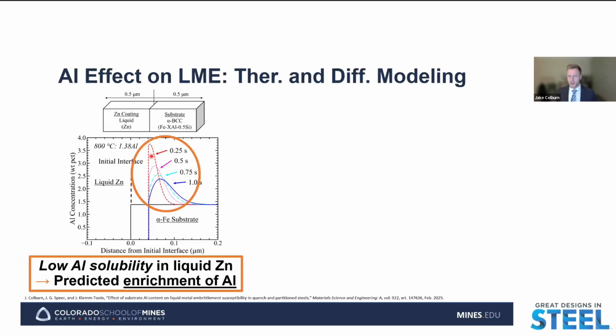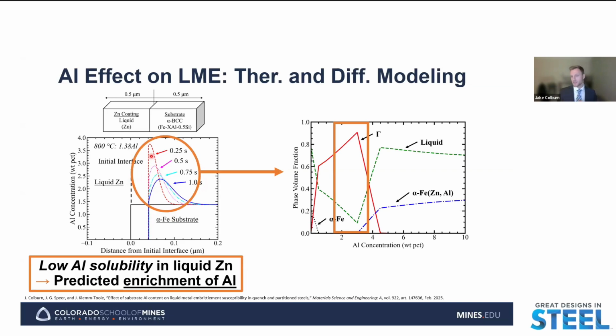So again, if we expect a change in that local composition at the interface, we can expect that there will potentially be a change in what phases are present and the equilibrium fraction of those phases present at the interface. And so again, like before with silicon, we can calculate the phase volume fraction versus the aluminum concentration at the interface. And rather than seeing that monotonic behavior that we saw with silicon, where increasing silicon content decreased the gamma phase stability across all the compositions, here we see that there is an intermediate range of aluminum concentration at which the gamma phase has a higher stable volume fraction than the liquid phase.